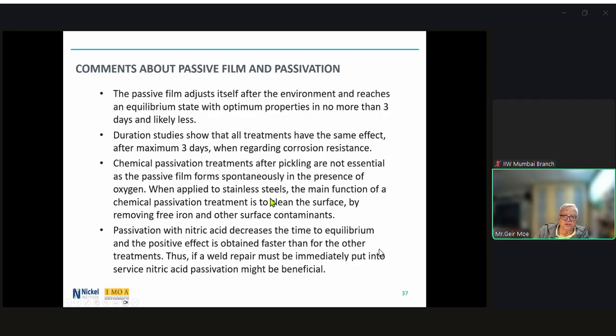Passivation with nitric acid decreases the time to equilibrium, and the positive effect is obtained faster than for other treatments. Thus, if a weld repair must be immediately put into service, a nitric acid passivation might be beneficial in providing the optimum corrosion resistance to that material when it's put back into service.